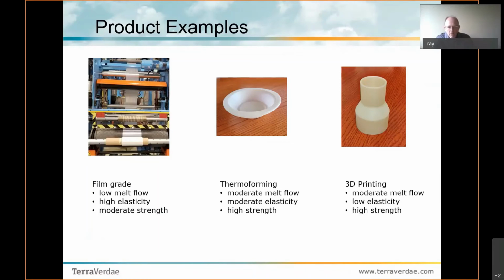The object on the right is a hose adapter that we made using our 3D printer from the filament that we produced. So we have a 3D printing filament that we are able to produce within industry specifications, and it ran just fine in our 3D printer. This is a material that would have a moderate melt flow and be quite a more rigid plastic, so low elasticity and higher strength. I use this for my shop vac actually, and it works very well.